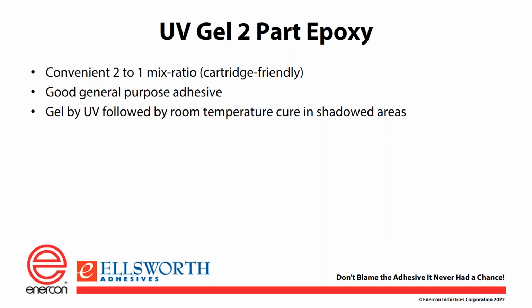The UV gel two-part epoxy. We've actually made a UV gel two-part epoxy and a urethane. So this is typically applications where somebody is using, in this particular case, an epoxy adhesive, and they're, say, shooting it into a small sensor. And the material is getting underneath the board, and it's taking either a heat cure oven or 12 to 24 hours to polymerize. And some smart engineer decides, hey, I'd rather do this thing quicker. So we modify the product so that once it fills the device, it's hit with UV radiation. It polymerizes on the top surface. The product can then move down the line, go to secondary processes, and the secondary cure completes after a period of time.